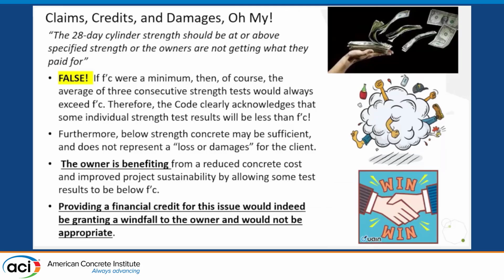So the claim is that the 28-day cylinder strength should be at or above specified strength, or the owner is not getting what they paid for. This is false. If the f'c were the minimum, then the code would never accept something less than f'c, and as it clearly states in the code. Furthermore, below strength concrete may be sufficient and does not represent a loss or damage to the client. This perception in the public or in the client's idea is like, well, I got something less than what I paid for, I got a damage, you owe me money, but it doesn't go the other way.